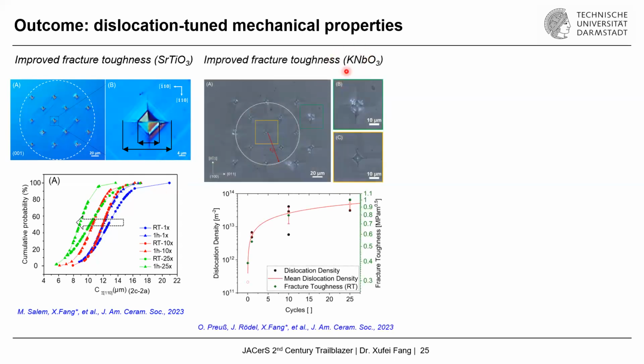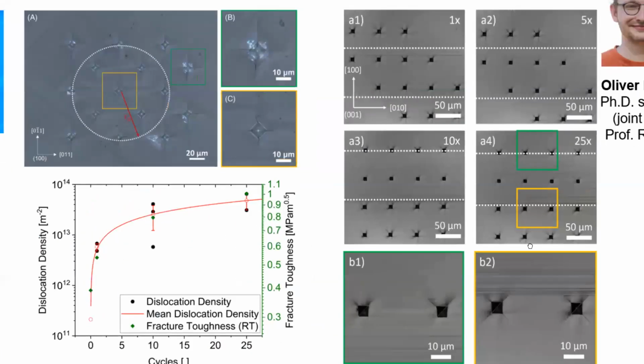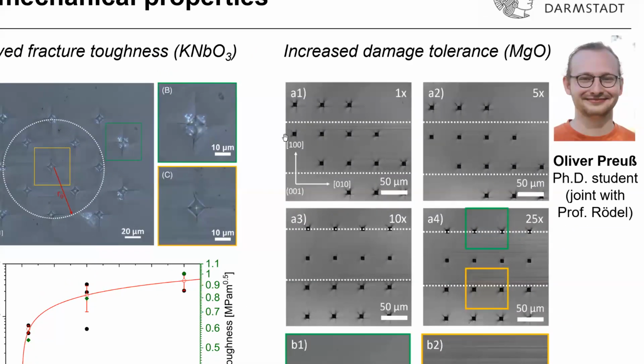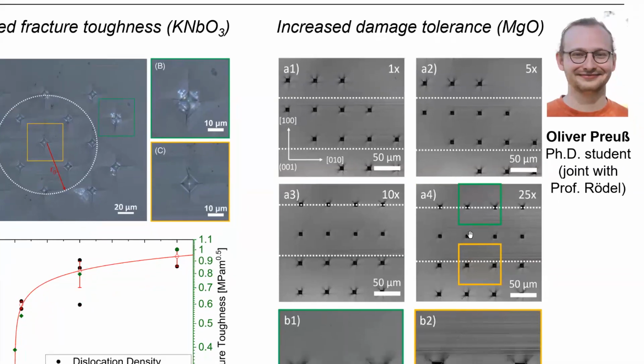And also we see a similar trend for potassium niobate. After engineering dislocations, we also see the crack shortening, which is even much stronger than strontium titanate. And we even see almost 2 or 3 times higher fracture toughness in the dislocation-rich regions compared to the dislocation-poor regions. And what's more interesting is if we look at magnesium oxide, once we engineer the dislocations within this region, as indicated by the dashed lines, after 1 cycle, we have a rather low dislocation density, up to 25 cycles, very high dislocation densities. What's interesting is the cracks even completely disappeared. So that means we have a much, much higher damage tolerance if we can pre-engineer high dislocation densities.